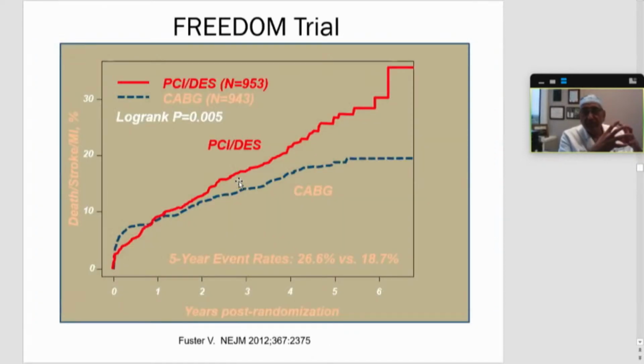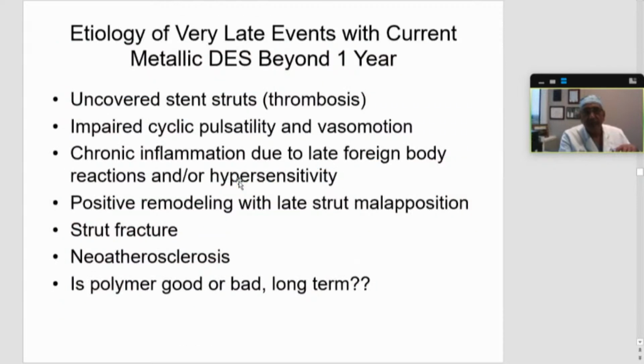In the FREEDOM trial, one of the reasons why we did not do so well with drug-eluting stents may be because of this crossover. After 2 years, there was a clear benefit of reduction of events in the CABG group, while PCI with DES continued to have event rates, most of them driven by target lesion revascularization.